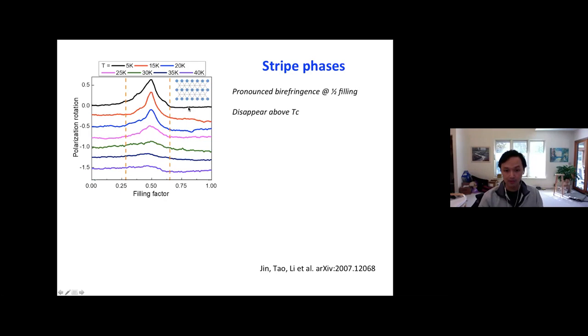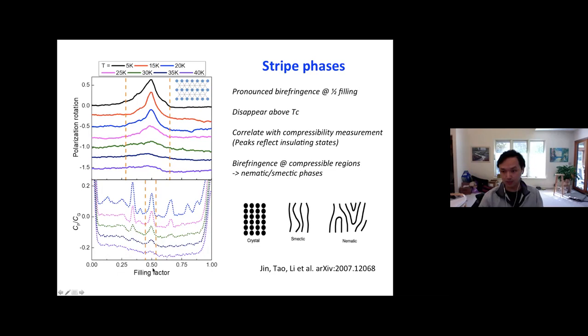What's actually interesting in this data is that when you compare with the compressibility measurement, the incompressible state at 1/2 filling is very sharply distributed in the filling factor. But this peak is much broader compared to the incompressible state at filling factor 1/2. What it means is that even in the compressible region of this system, it still breaks rotational symmetry. So it really suggests that the system is some kind of liquid crystal state in between these compressible and incompressible regions. Well, we can also image the domain structure.